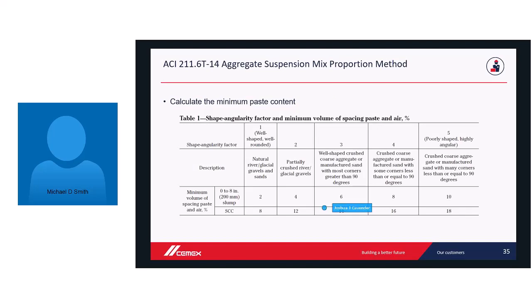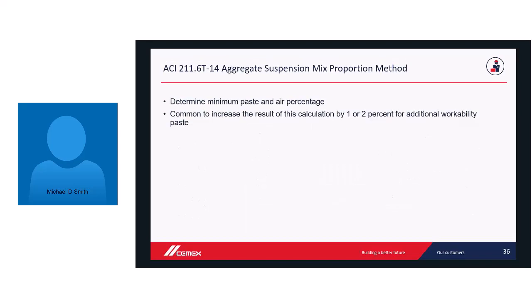You do the same thing with your other aggregate source, and then you come down here and you get your minimum volume of spacing paste plus air. So if you're doing an SCC mix and your average of your aggregates is a 3 visually, you'd be about a 14% paste factor here, or 6% if you're just doing a normal 0 to 8-inch slump mix.